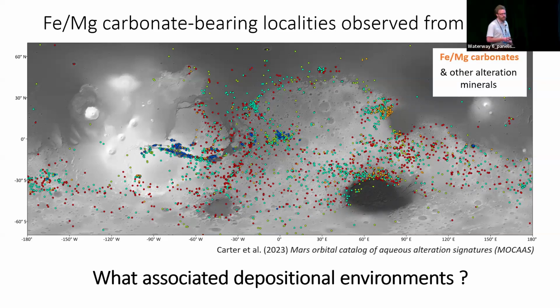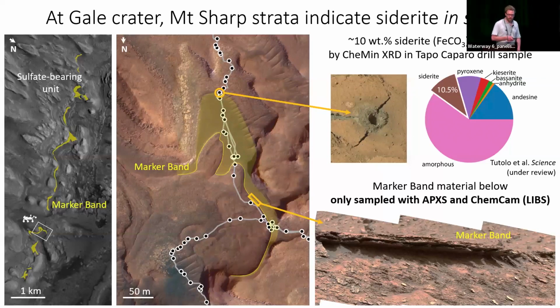And unfortunately, so far it's been really hard to make sense of how they form. Namely, the environment that's associated with them has been elusive. And it turns out that Curiosity at Gale Crater has a lot to offer on carbonates, actually. So you've probably heard of that. That's been told in the past couple of years, that we came across the marker band. We've been tracking that band from orbit for a long time, and so now we've gone through it. We did a campaign there, and when we drilled just above the marker band, it's almost part of the stratigraphy here. That's where we identified using X-ray diffraction 10 weight% siderite in the bulk of that sedimentary rock here.